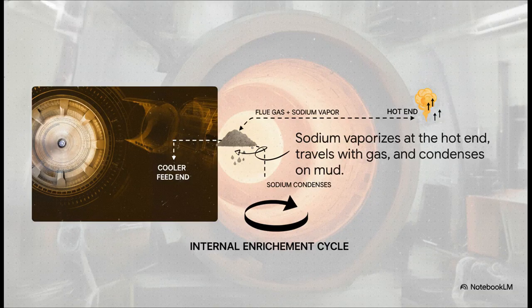This diagram here, this is really important. It shows how the sodium problem just compounds on itself. Down at the hot end by the burner, the sodium vaporizes. Then that vapor travels with the hot gases toward the cooler feed end of the kiln. And what happens? It condenses back onto the fresh, incoming lime mud. So you get this internal enrichment cycle that concentrates the sodium right in the middle of the kiln. It's the absolute worst place for it to build up.